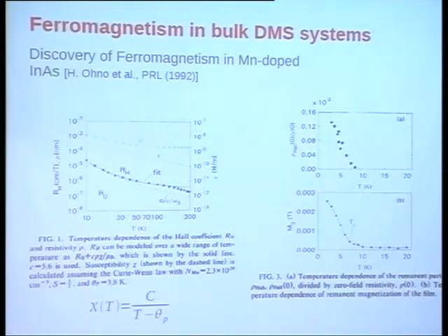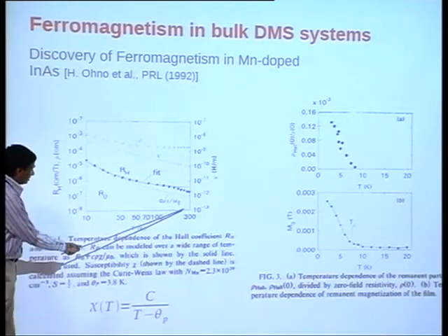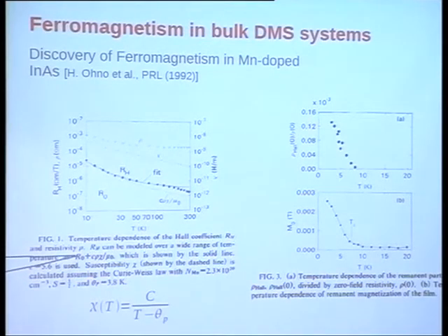Okay, so this is the first paper I know reporting discovery of ferromagnetism in Mn doped semiconductors. This is Mn in indium arsenide. And here's one of the graphs from the paper. It shows the Hall constant as a function of temperature, and the Hall constant has been fit to an empirical law of this kind. There's a constant part, and there's a part that is proportional to resistivity times the susceptibility.